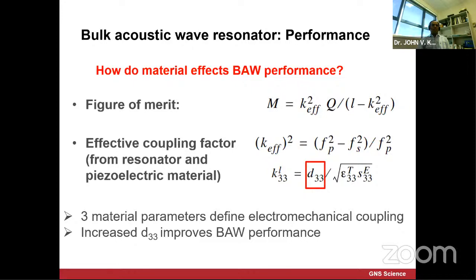The D33 parameter is normally related to the material strain. Then you have epsilon, the dielectric constant, and you have this called KEF, which is basically about resonance losses. So there are quite a few factors, but the key factor is D33.